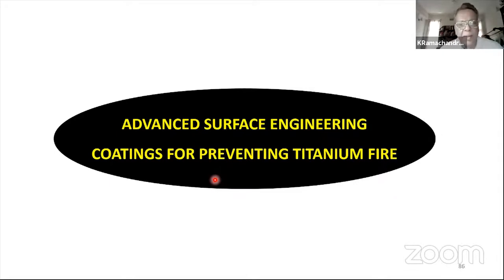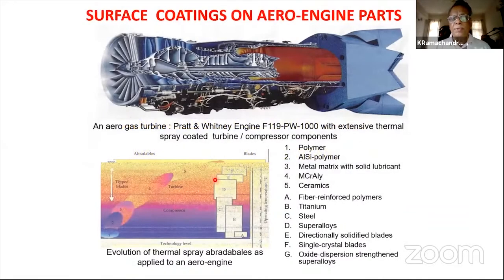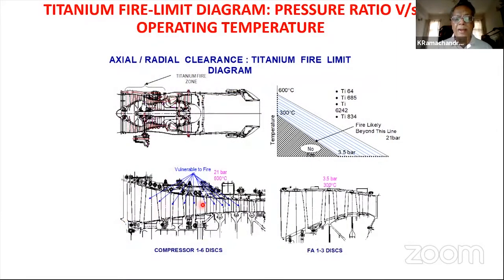Sorry about that. So then there are coatings which are important. If you look at the engine, it's a plethora of coatings, hundreds of them, coating all over. We don't notice them, but they're doing all sorts of functions at each location. And one important thing is the coatings which are there on blades. If you typically look at a compressor or the fan, the blades are made of titanium because we need low weight parts. And similarly, the casings are also made of titanium today. And if you look at the temperature in the compressor area, it could be anywhere between 300 to 600. And the pressure in the compressor area is about 3.5 to maybe 25.